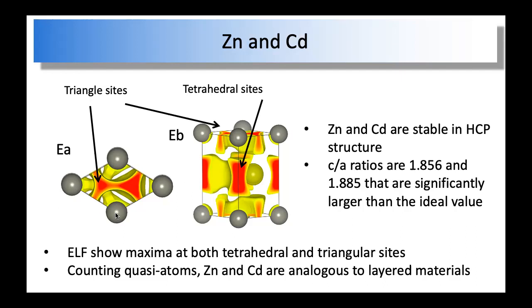Okay, remember the general trend of electron localization. If you have a larger lattice, then it always tends to localize in between 2 atoms. But once you decrease that, it starts to move to the sites that have more neighboring atoms, right? So it shifts from 2 to 4 to 6 to 8. And for HCP, zinc and cadmium actually also have a very strong electron localization at a site that has 3 zinc or cadmium neighbors. And because of that, this site also has very strong interaction with the electron localized at the tetrahedral sites.